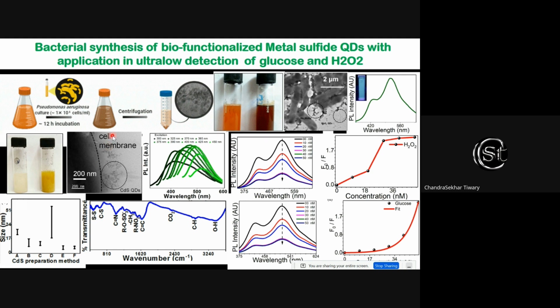Now we can easily separate the microbe from the quantum dot using centrifugal separation, and in the size plot shown here, you can clearly see different methods of synthesis and the size distribution. Now the current method not just gives a good quantity, it also has a very narrow size distribution, and it can be utilized for several biomedical applications. For example, we are utilizing it for glucose or H2O2 sensing, and the transmission electron microscope image shown here clearly shows the quantum dots forming on the surface because of the microbe interacting with the salt and producing a controlled size quantum dot.